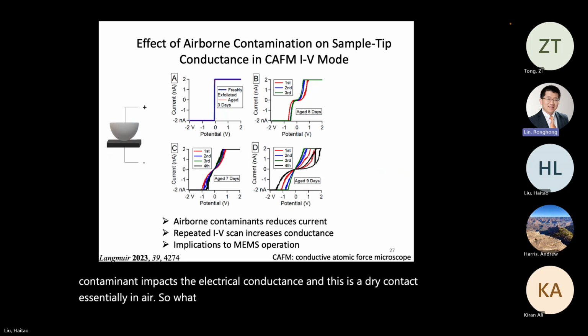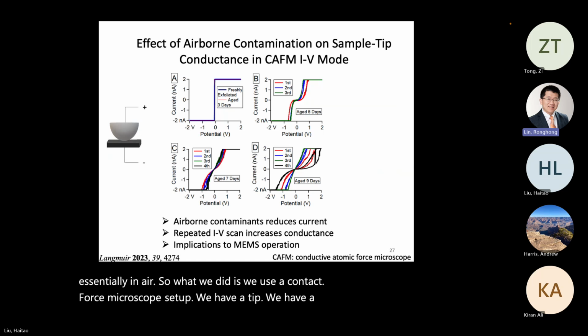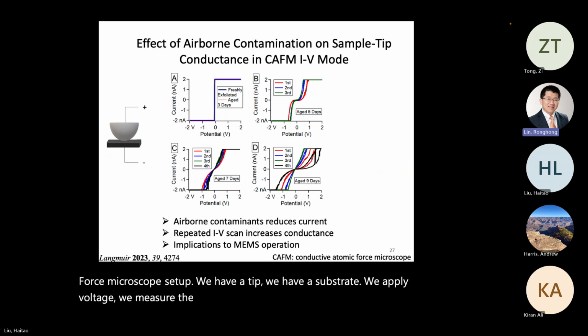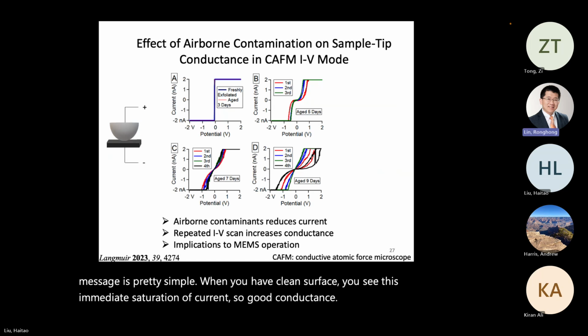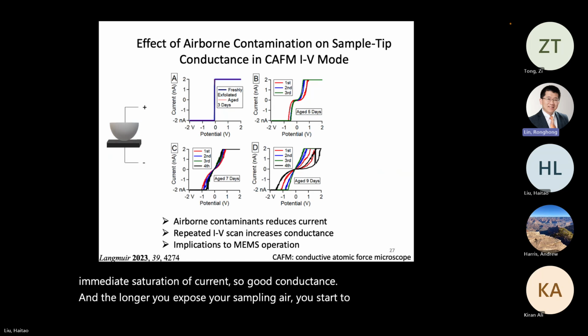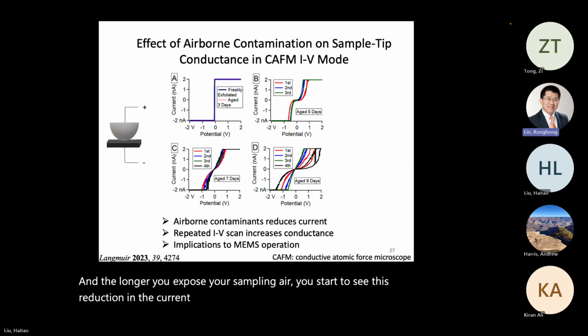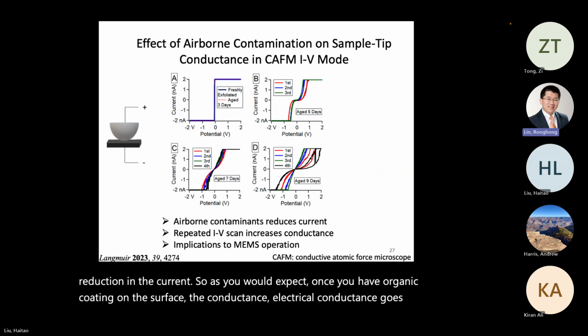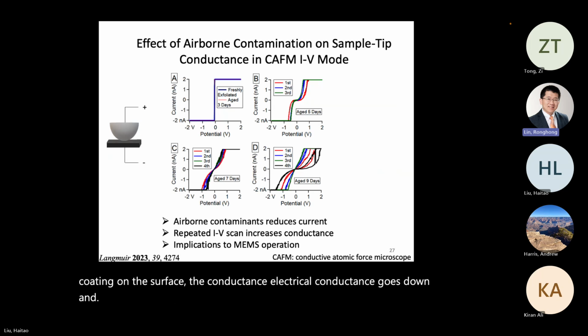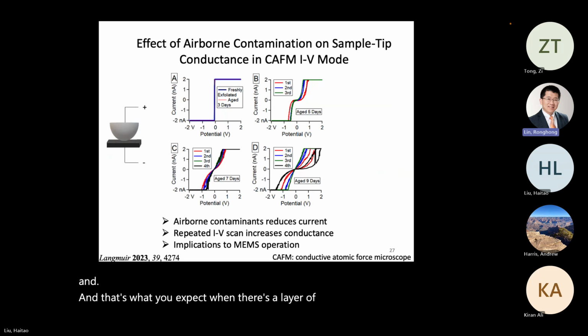So what we did is we use a conductive AFM, atomic force microscope, setup. We have a tip, we have a graphite substrate, we apply voltage, we measure the current. Okay. And the results are in the middle, and the message is pretty simple. When you have a clean surface, you see this immediate saturation of current, so good conductance. And with longer exposure of the sample in air, you start to see this reduction in the current. So as you would expect, once you have an organic coating on the surface, the electroconductance goes down, and that's what you expect when there's a layer of oil on the surface.